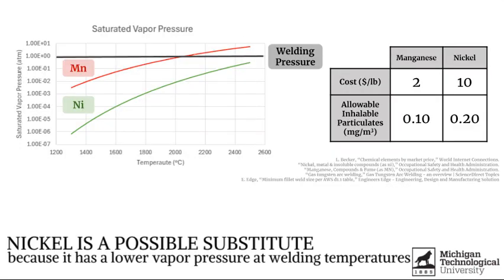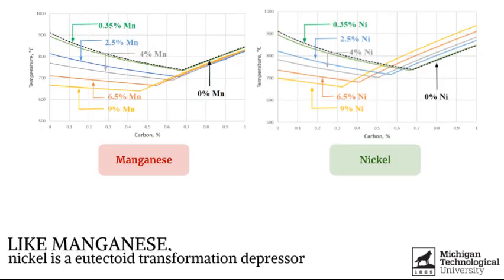Nickel is one possible substitute for manganese that our team has been exploring. It has a lower saturated vapor pressure than manganese in welding conditions. This means it will not vaporize in the welding process. However, nickel is 5 times more expensive than manganese, so we are trying to find the balance between health risks and cost. Similarly to manganese, nickel also lowers the eutectoid transformation temperature, which again promotes nucleation and growth of the ferrite during cooling. This leads to a finer grain size in the microstructure, which helps strengthen the alloy.